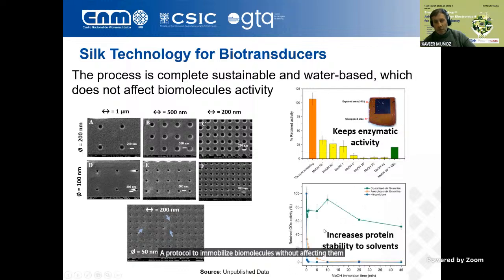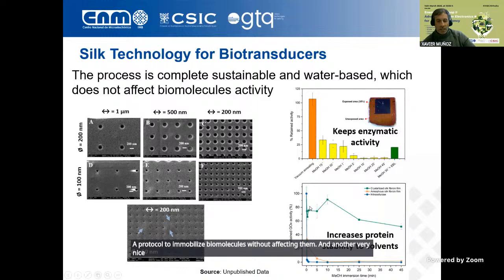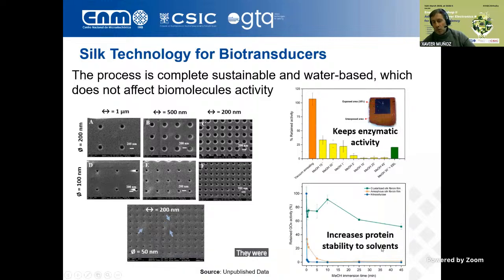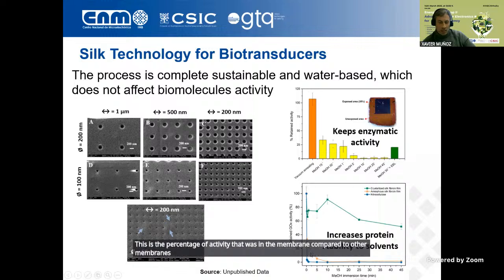And another very nice thing was that once immobilized inside the membrane, they were stable even to the action of solvents. As you can see here in this green image, this is the percentage of activity that was in the membrane compared to other membranes like an amorphous silk, that was not crystalline, or nitrocellulose. And we were improving this stability a lot.